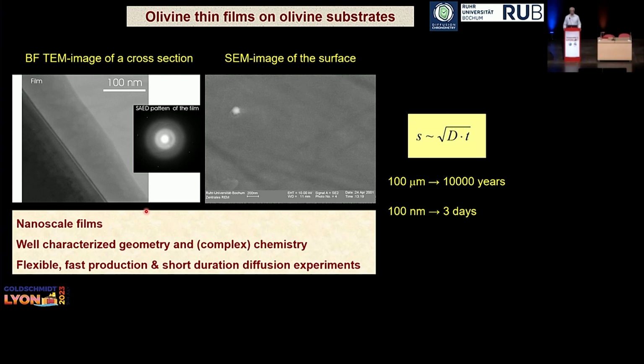So on your left, you're seeing a thin film of an olivine on an olivine of two different compositions. And the scale is about 100 nanometers. And these are very easy to produce, very quick to produce, very flexible. You can produce all kinds of minerals. And so that has opened up things that you do in diffusion studies that you couldn't do before. And the right image shows you an SEM image. You don't see anything in that image. And that actually is exactly the point. The surface is extremely smooth. It has a roughness of plus or minus 1 nanometer.